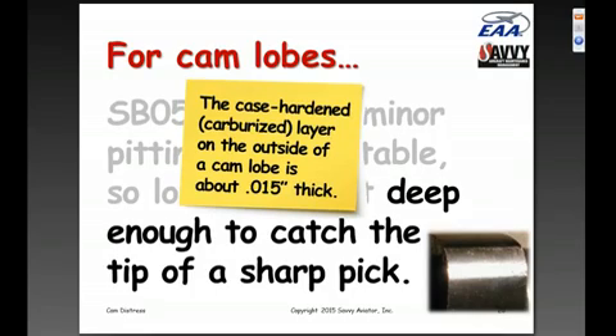Now again, the logic behind this guidance in the service bulletin, as I mentioned before, is that cam lobes are made with steel that's moderately soft on the inside, but then case hardened through carburizing to create a very hard outer wear surface. And that case hardened outer layer that's created through the carburization is about 15/1000 of an inch thick. So if the surface is pitted, but the pits aren't deep enough to penetrate that hardened layer, then the cam lobe is probably okay, and it probably will continue without coming apart. But if the pit gets deep enough to penetrate the carburized layer and get into the softer inner meat of the cam lobe, then that cam lobe is going to come apart.